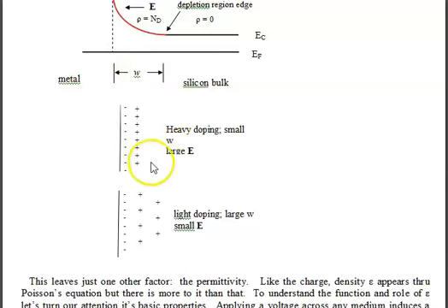The first one on top is the case where we have heavy doping. Now, the critical issue in all of this is that in order for the Fermi levels to equilibrate between the metal and the silicon, there is a certain fixed amount of charge, for the N-type, a fixed amount of mobile electrons, which are transferred from the silicon into the metal, independent of doping. A certain number of charges have to be transferred from the silicon into the metal.